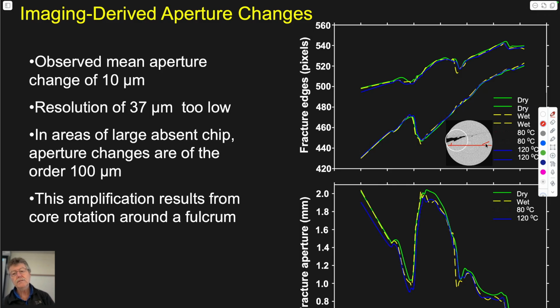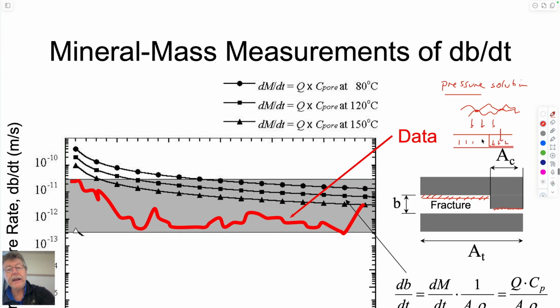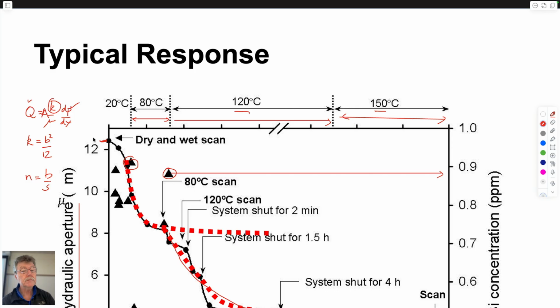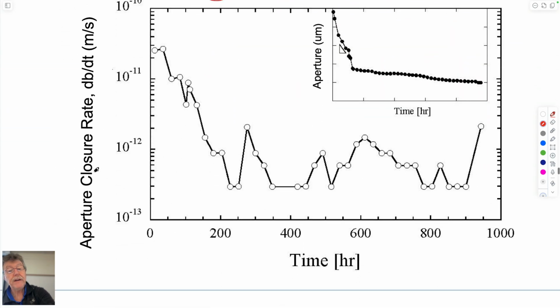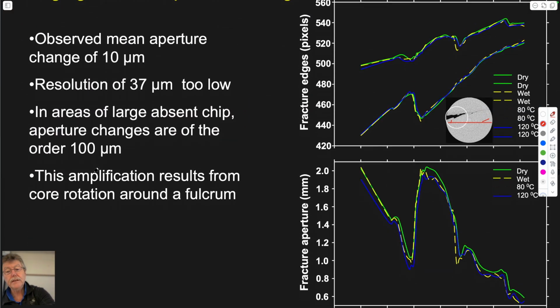And so this sample was 2 centimeters in diameter. So I think it was something like 20 millimeters. So it's 20 microns resolution. You saw earlier that the fracture starts out at something like 12 microns. And so 1 pixel in the CAT scan is actually bigger than the fracture itself. And so all you can pick up in CTing it is a trace, which you can see here. This happened to be a chip within the sample where it was broken, which gives this big hole. But most of the sample that was flowing, this wasn't continuous, or it wasn't contiguous all the way along the sample. It was just on a small length of the sample.